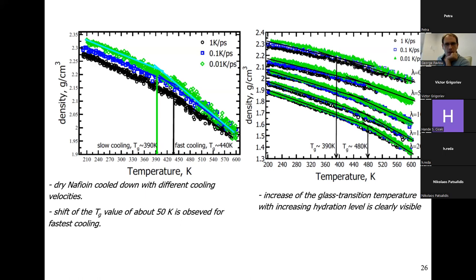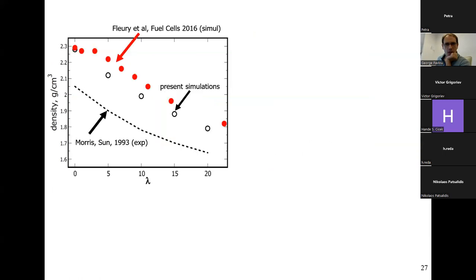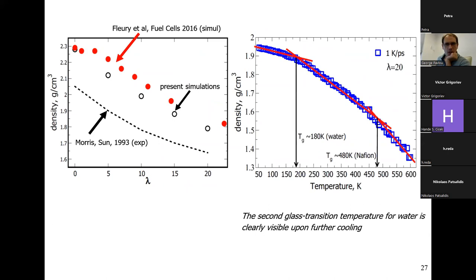Why do the Canadian group see plasticization while we see anti-plasticization? I decided to cool further to investigate. First, checking our density values: our results are not far from the experimental results of the Fleury group — a reasonable ballpark, though force fields are not perfect. Cooling to very low temperatures reveals a second glass transition event at low temperature, which we associate with the glass transition of confined water.